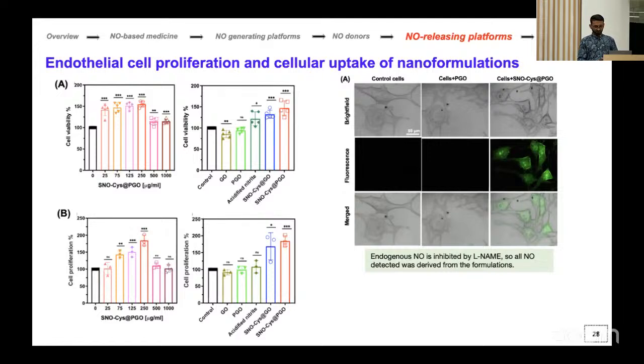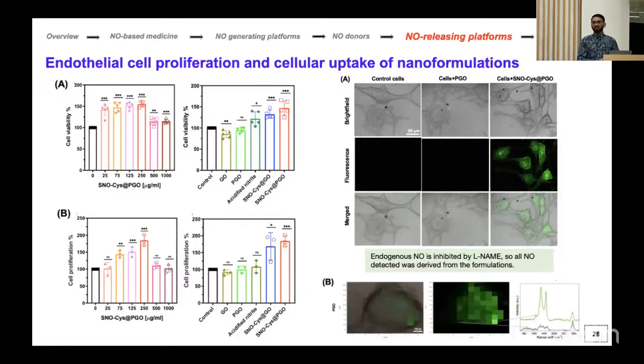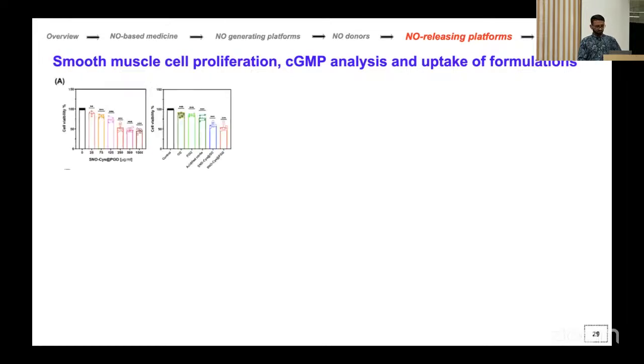So where does graphene go? We used Raman imaging mapping, because graphene has a very strong Raman signal. We show that the bright green signals show the uptake of graphene. And then we look at the smooth muscle cell proliferation, because we want to reduce the proliferation of smooth muscle cells. We show using MTT assay that it is reducing the proliferation of smooth muscle cells.